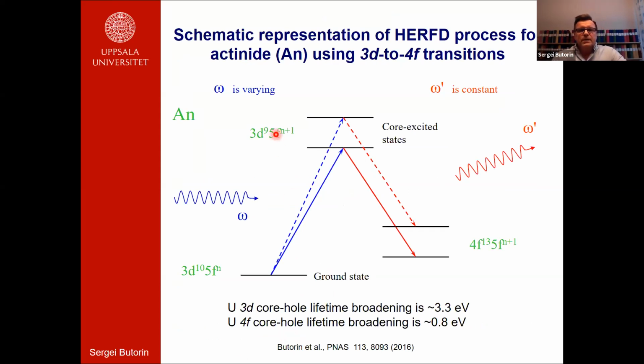So this slide shows the schematic representation of the HERFD process for actinides using 3d to 4f transitions. If we tune the energy of the incident photons to the 3d threshold, the system, by absorbing a photon, can be excited into high energetic states with the 3d core hole. And this step actually corresponds to doing X-ray absorption spectroscopy.